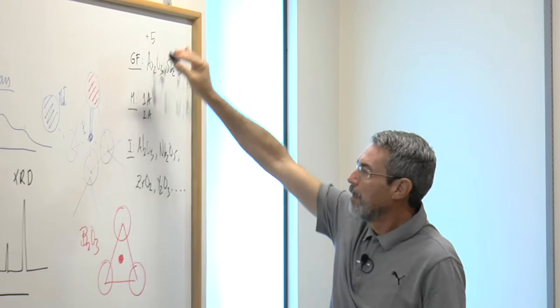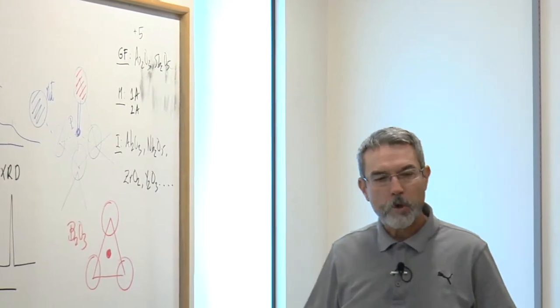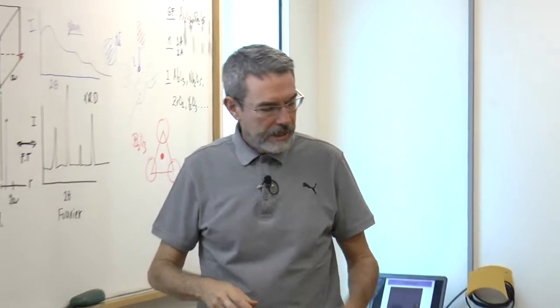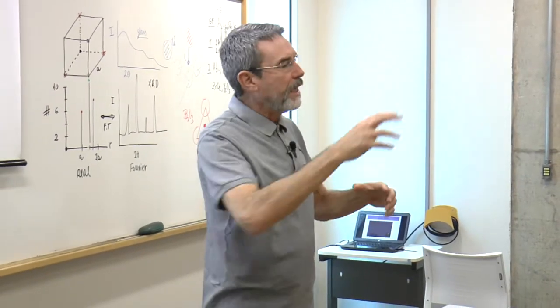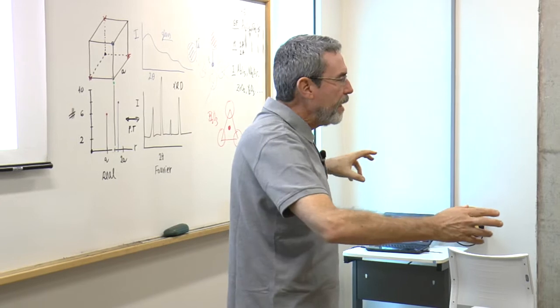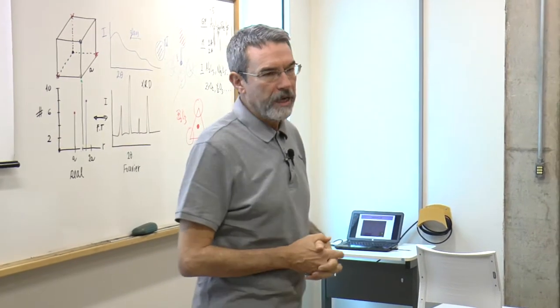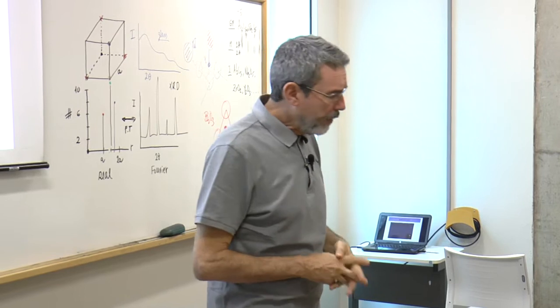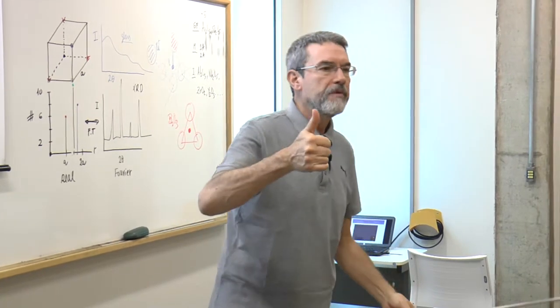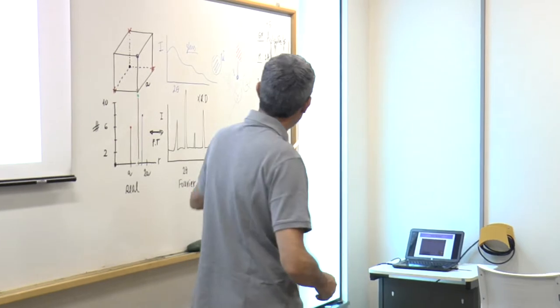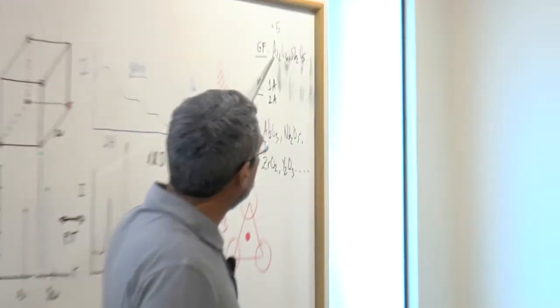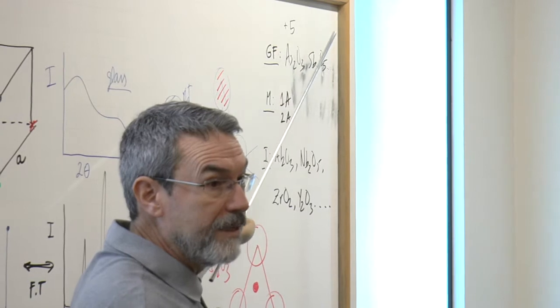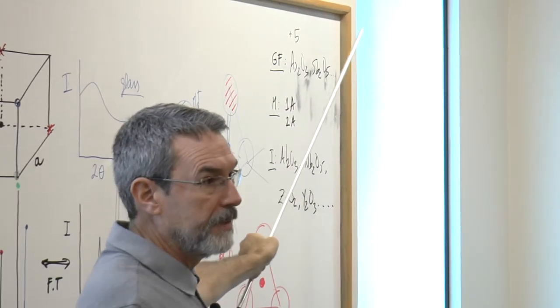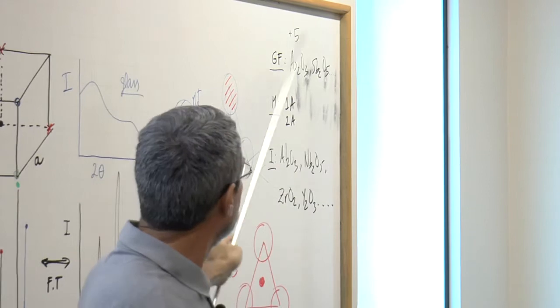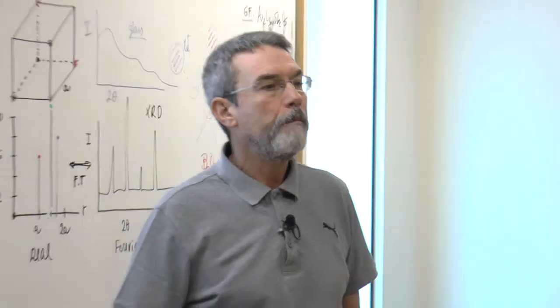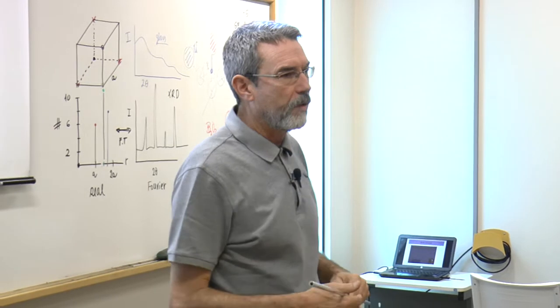In general, to make commercial glasses, one adds a combination of glass-forming ions, intermediates, and modifiers. And by the way, as a rule of thumb, 50% or so in mole of these guys here to make a decent glass, as a rule of thumb. There are some glasses with a little bit less, but 50 or more molar percent of glass forming oxides.